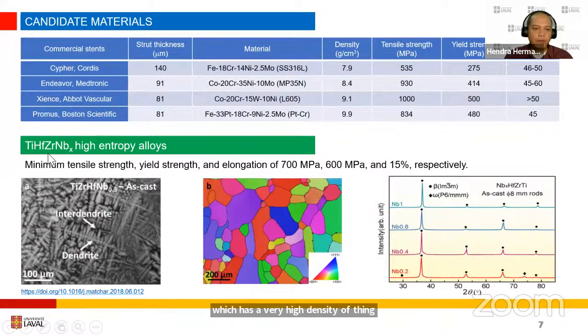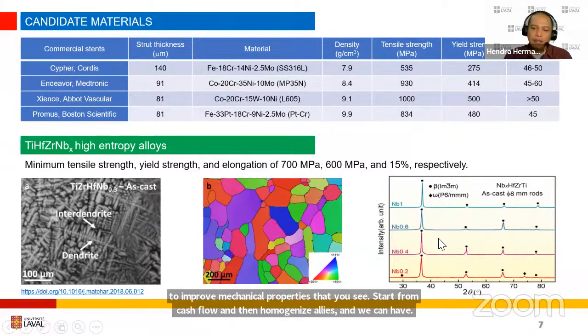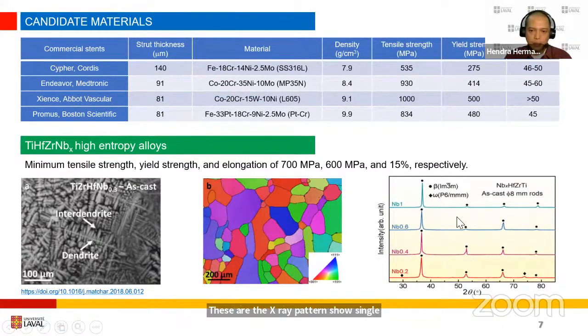And for us, we propose this titanium, hafnium, zirconium, niobium high entropy alloy, which has a minimum tensile strength, yield strength, and elongation of 700 megapascal, 600 megapascal, and 15% elongation respectively. So it's quite high, and these are the values obtained from homogenized alloys. It's not yet treated to improve the mechanical properties. You see, starting from cast alloy and then homogenized alloys, and this is the X-ray pattern, showing a single phase, with some small phase that is detected, but at very, very low concentration.